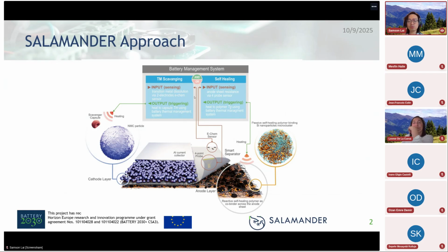And then we have another self-healing polymer that's throughout the entire anode, and that's for helping the overall properties of that electrode. On the cathode side, our approach to self-healing is focused on these scavenger capsules or microvesicles. These are carrying some sort of active species or sacrificial lithium salt, and it's targeted towards some degradation mechanism on NMC cathode.